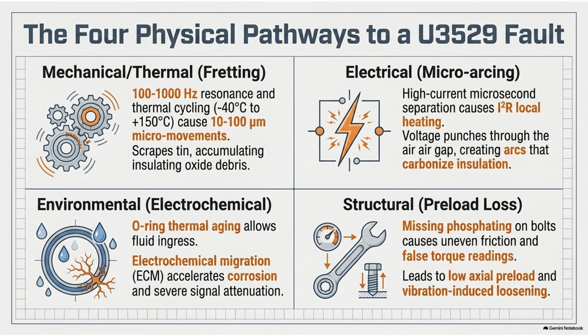Rubber is durable, sure, but it's not invincible. Not at all. Under those extreme thermal shocks we mentioned, the rapid swings from -40 to 150 Celsius, the fluoropolymers in the rubber begin to cross-link and age. It degrades. The rubber hardens. It loses its elasticity. Eventually, microscopic microcracks form in the O-ring itself. The mechanical seal is compromised.